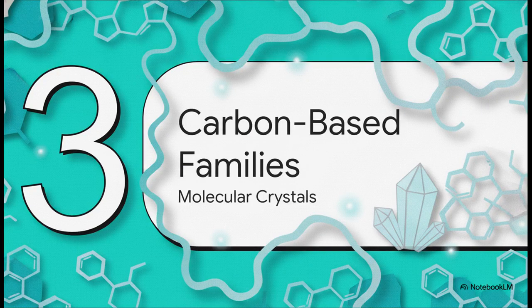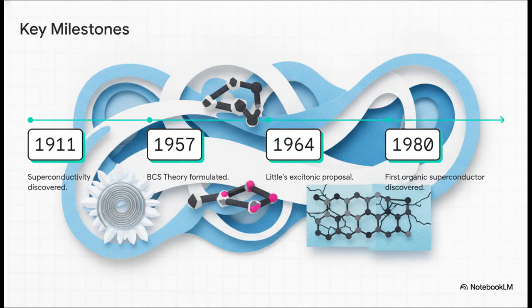Which brings us to Section 3, carbon-based superconductor families. Looking at how this all unfolded historically, superconductivity itself was discovered way back in 1911, and scientists finally nailed down a theory for it in 1957. Then, boom, Little drops his bold proposal in 1964. But it actually wasn't until 1980 that a team led by Denis Jerome finally discovered the very first true organic superconductor. Now, it was a quasi-one-dimensional organic salt, and sure, it only worked at around 1 Kelvin and under intense pressure, but it proved the core concept: carbon-based materials absolutely can superconduct.